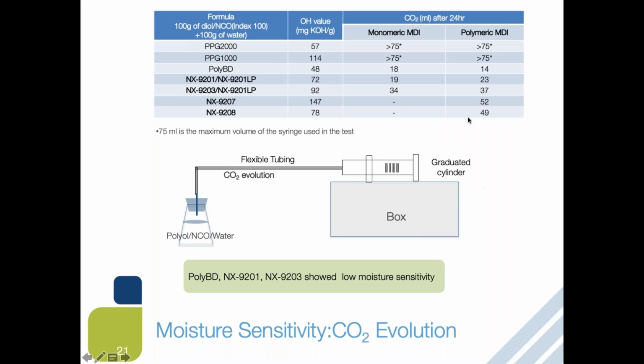Earlier, we showed this mini study with the polyols, and we also did the same kind of study with the diols. So as you can imagine, polyether diol is very hygroscopic and loves water. Therefore, you can see the CO2 evolution numbers are very high, so very moisture sensitive. Now, as you can expect, poly-BD has shown the least moisture sensitivity, followed by 9201 and 9203, and also the other grades. So this also proved that diols with the greatest hydrophobicity tend to have the least moisture sensitivity.